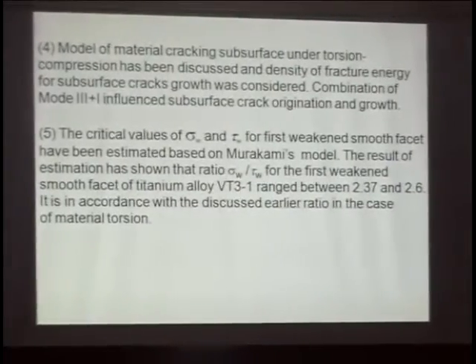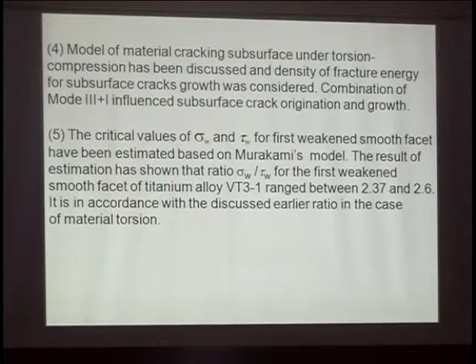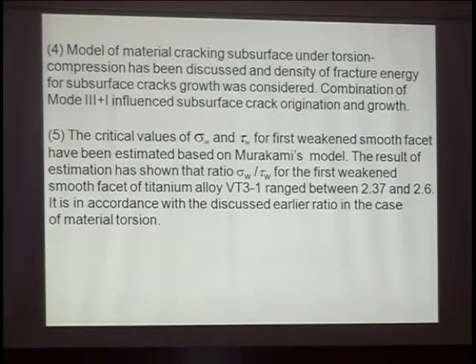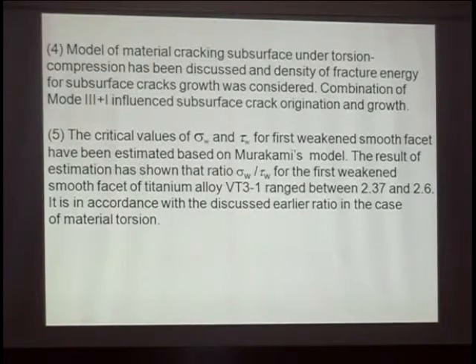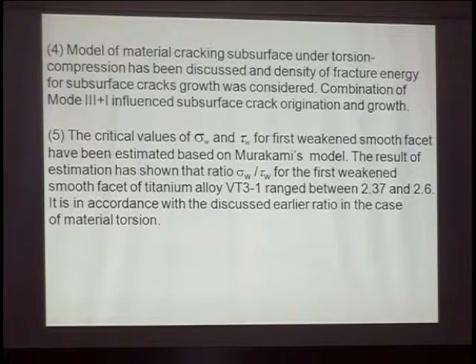You have used a notch specimen with a notch tip radius equal to 2 millimeter. Yes, 2 millimeter. If I use a notch radius equal to 1 millimeter, for example, 0.5 millimeter, is it possible to have a subsurface crack? Thank you very much. Absolutely right. It depends only on the level of external stress at which this transition will occur. For a lower radius, the transition will be seen at a lower level of stress, but it will always occur, independent of the material state and surface. It depends on the possibility to realize one of the manners of material cracking.